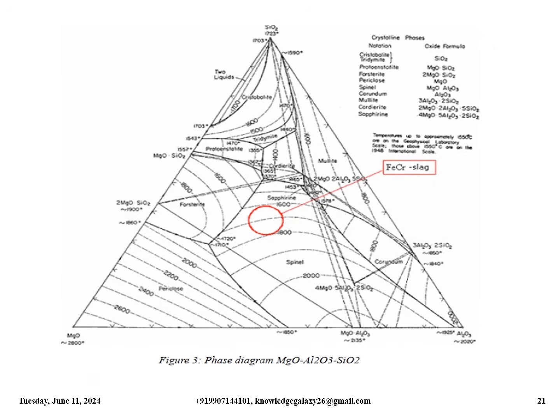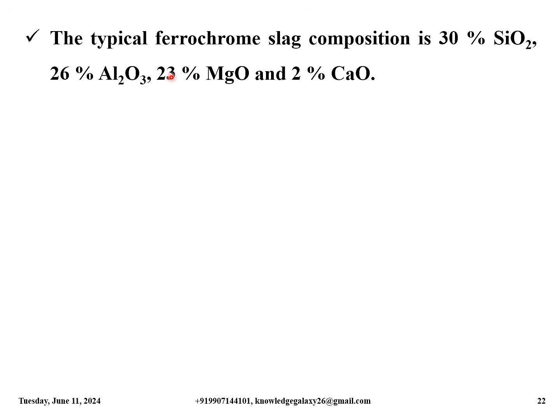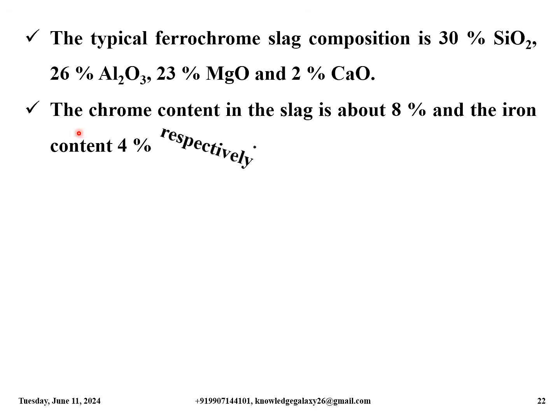So this is the typical phase diagram of MgO, Al2O3, SiO2 in the ferrochrome slag phase, and you can observe it in detail. Then this is the particular region where the ferrochrome slag is obtained. Okay, going good. Let's move on. The typical ferrochrome slag composition is 30% SiO2, 26% Al2O3, 23% MgO and 2% CaO. The chrome content in the slag is about 8% and the iron content is 4% respectively.